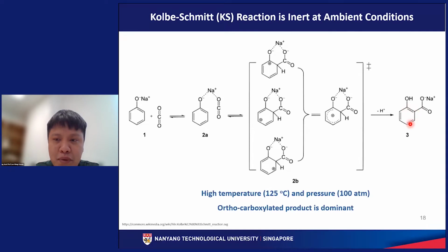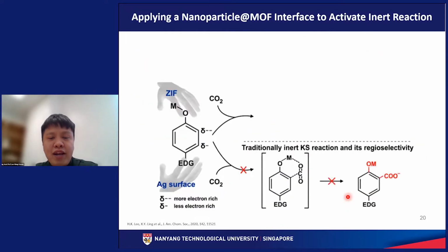Okay, so this is ortho, meta, and para. In this case, due to the formation of the 6-member ring intermediate, almost always the ortho-carboxylated product is formed. In other words, the ortho-carboxylated product is the most dominant product in this particular reaction. Another point to note is that for this reaction to occur, it requires high temperature of 125 degrees Celsius, as well as high pressure of 100 atmospheric pressure. So in other words, KS reaction is inert at ambient conditions. Okay, so our main aim here is to use our pseudo high pressure microenvironment to drive KS reaction even at ambient operating condition. So again, traditional KS reaction cannot occur at ambient condition, and it always forms the ortho-carboxylated product.